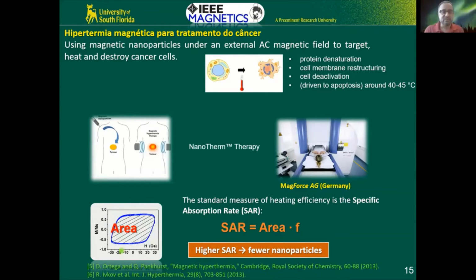Now, if you look at this one right here, don't think of the magnetization curve for nanoparticles that you can measure in a SQUID or a VSM. That is the DC curve, right? So that one, obviously, if it's superparamagnetic, there is no hysteresis. Here, what we're talking about is the AC response. So this hysteresis here is due to the high frequency of the field.